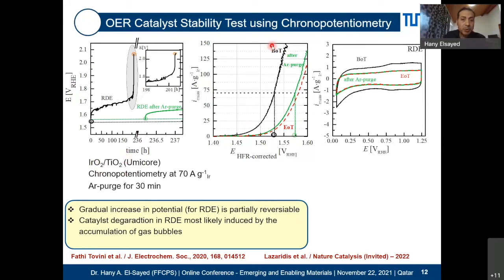And what we did in this experiment is that we started with applying a constant current. And of course, similar to literature, what you find is the following. This is again in RDE, so the potential keeps increasing slowly, and then we go through this potential jump. How long does it take? It took 9 days of measurement in RDE. And for those of you who are using RDE, I'm sure you know what it means to keep measuring this at 40 degrees, by the way. This measurement was done at 40 degrees for 9 days. It's a pain. But anyway, we do this experiment.